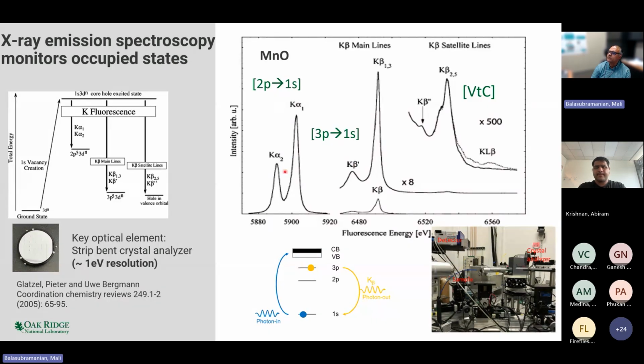These two other emission lines, the K alpha and K beta, also have some ligand sensitivity, but their major sensitivity is to the spin states of the electrons in the 3d orbitals, and in some cases to oxidation state. So you can do these measurements using all these different emission lines. You can also do them resonantly or non-resonantly. So there is a whole gamut of experiments which fall under this one broad topic, which is called X-ray emission spectroscopy.